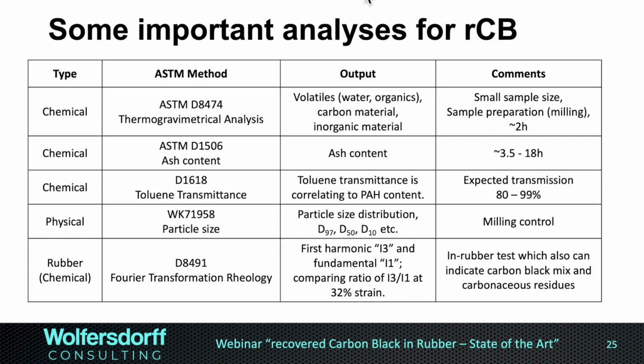And so this is really the summary of the important analysis I see for the recovered carbon black to process control, to do the quick testing. We have the TGA, thermogravimetrical analysis. The only downside really is the small sample size. Going into the TGA are milligrams, and they need to be representative for maybe a truckload or maybe for a whole production run of a continuous tire pyrolysis. So sample taking and sample downsizing to make it representative for the material and the production run, that is really key. TGA takes about 2 hours, which is good,